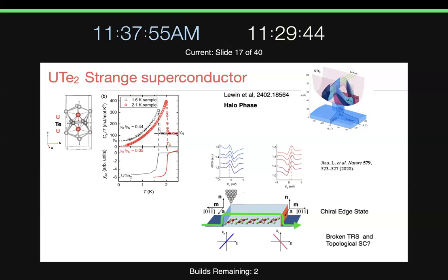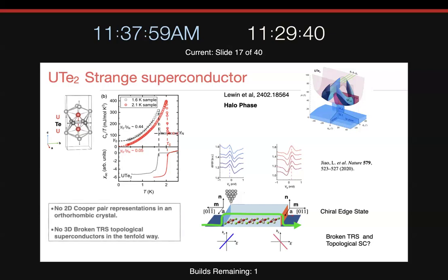But such a topological state poses headaches for our understanding. Number one, in this orthorhombic crystal, there are no two-dimensional Cooper pair representations. Furthermore, there are no three-dimensional broken time reversal symmetry topological superconductors in the tenfold way. So if these statements are correct, it's very difficult to accommodate them within a conventional picture of BCS pairing. So this is by way of motivation. If someone comes up with a very nice explanation in a conservative framework, I'll be the first to embrace it and say, that's fine, we understand it now. But at the moment, it seems to suggest that we need to think outside the box if we're to understand this material.